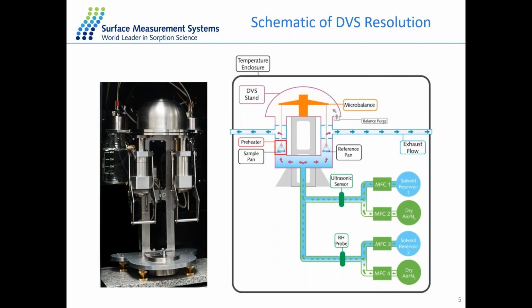So basically, we compared some commercial samples, like activated carbon or carbon black, and we do get very similar results compared to the nitrogen sorption technique. You may think the octane molecule is a bit larger, but in the ISO standard for BET determination, octane or some other organic vapor is written as a probe molecule as a standard for the determination of BET as well. Those organic vapors can be used at ambient temperature, and the nitrogen molecule can only be used at liquid nitrogen temperature. So one of the big differences between the two techniques is the condition to perform the experiment.